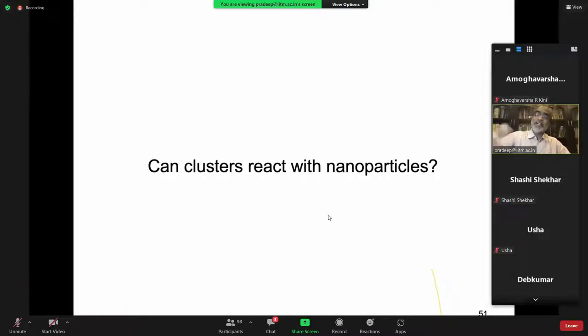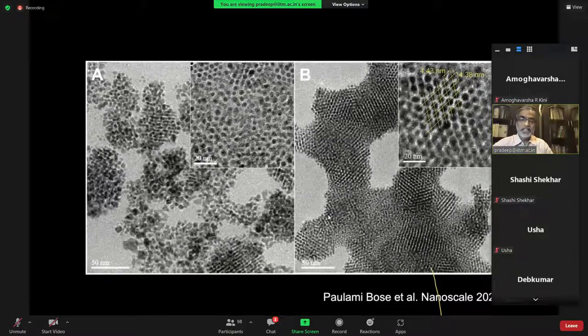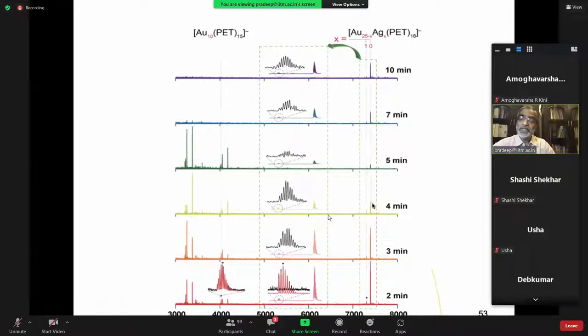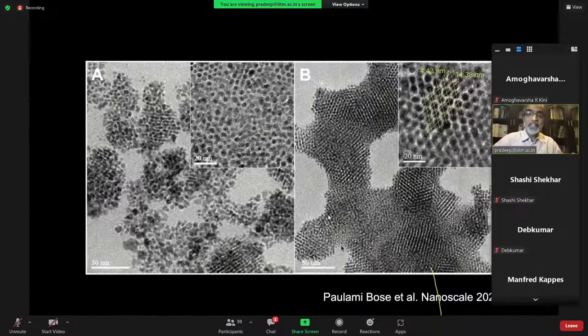Now, one can study many reactions, but where will it stop? Can clusters react with nanoparticles? We found that polydispersed nanoparticles, upon reaction with clusters, give a solution which is highly monodispersed, and you create superlattice structures. This happens because these clusters contribute to etching of atoms from these polydispersed nanoparticles and make them monodispersed. And you can detect, let us say, here is a gold cluster. It is added to gold 25, added to silver nanoparticle. You see one silver atom being picked up by this guy. And in that process, you create these cluster